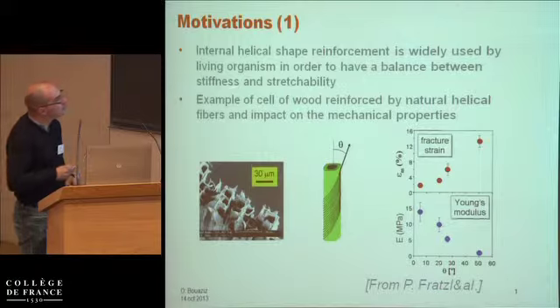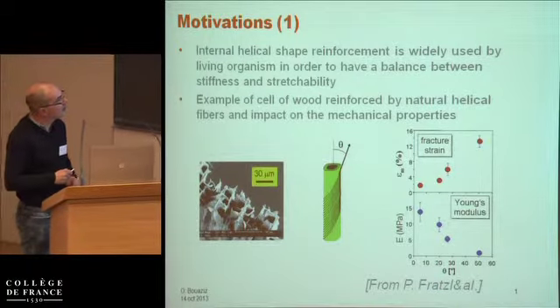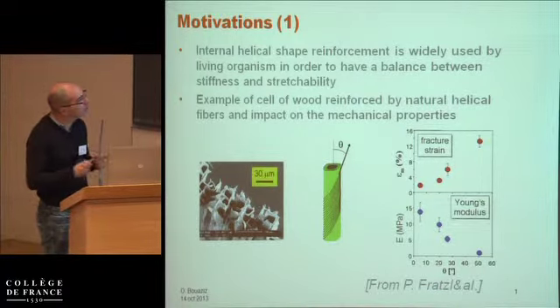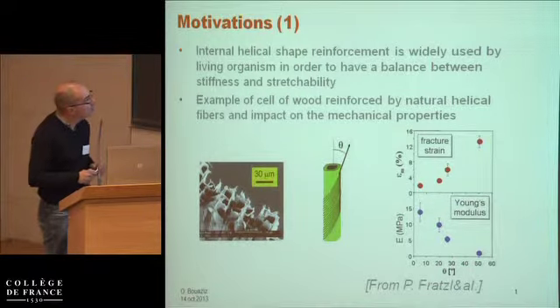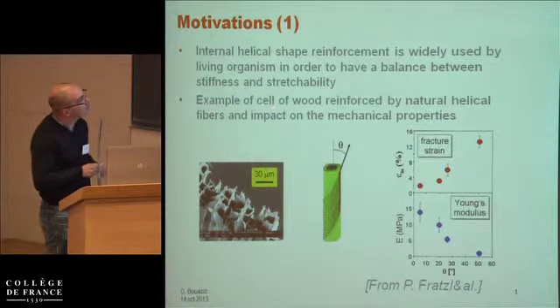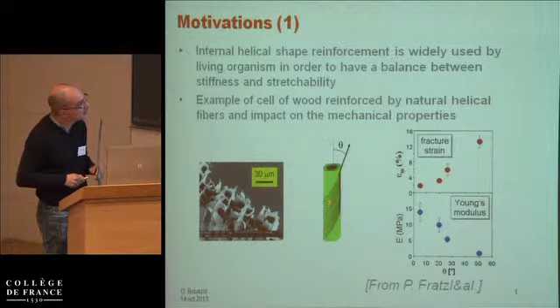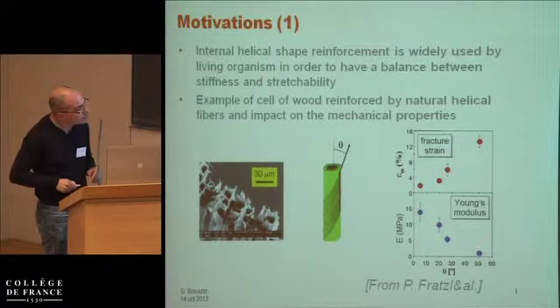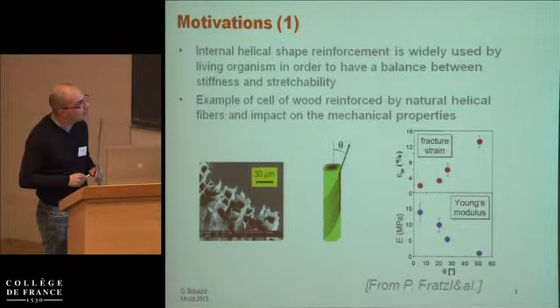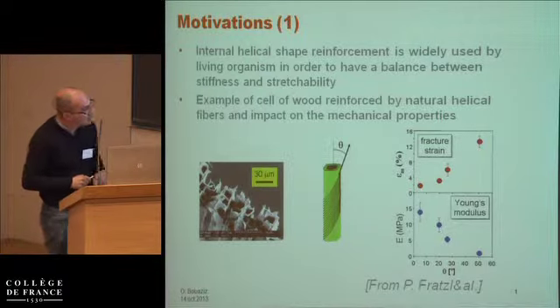Internal helical shape reinforcement is widely used by living organisms in order to have a balance between stiffness and stretchability. I take an example from Peter Fratzl, an example of a cell wall reinforced by natural helical fibers and the impact on the mechanical properties. Depending on the pitch angle of the helix, he has shown that you have a strong evolution of the Young's modulus, but at the same time, a large increase in the fracture strain.